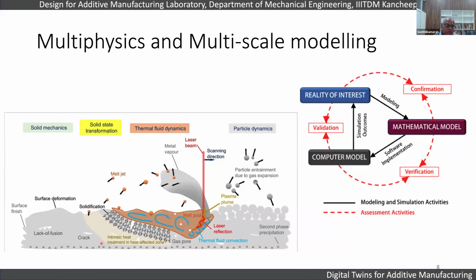And then you have solid state transformation happening here, which is the intrinsic heat treatment in the heat affected zone. After that solidification, you can see some microstructure formation and then defect formation here. And here is where the solidification kinetics can be used. You can see gas pores, where gas gets entrapped, gas induced porosity. And this is the process induced porosity because of the lack of fusion. So you can see all kinds of defects, all kinds of physics.